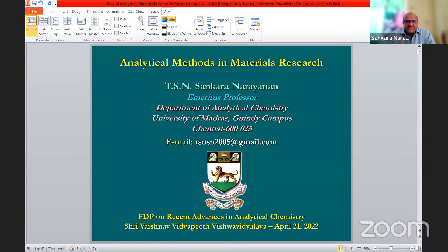So we prepared a simulated body fluid called Hanks balanced salt solution, and we added a small quantity of phenol red as an indicator. Phenol red is red in color. The pH of body fluid is 7.40, so we adjusted the solution to 7.40 and maintained the temperature at 37 degrees centigrade, which is body temperature. And we measured the change in absorption of the solution, because with the indicator added, it becomes a colored solution.